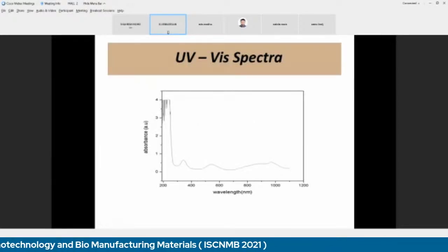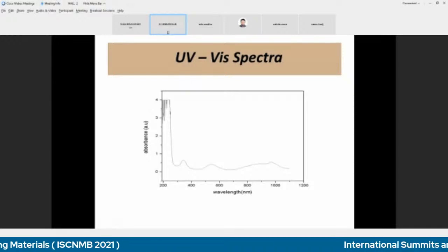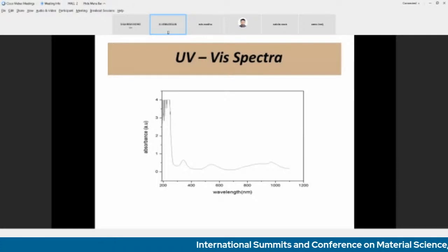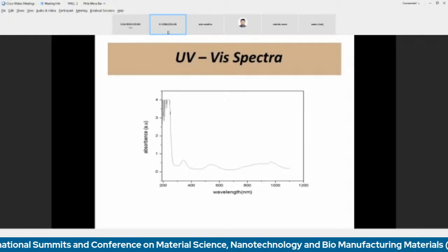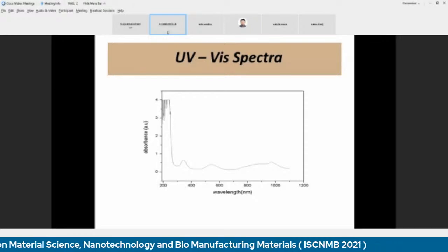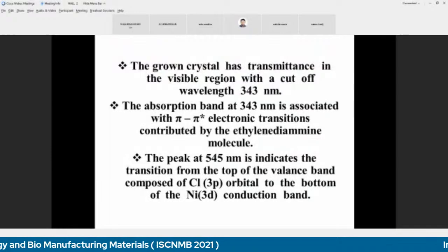Next, I am going to discuss UV visible spectroscopy. The UV visible absorption spectra was obtained on the ELICO SL 18 double beam UV visible spectrophotometer in the range of 190 to 600 nanometer at room temperature. From this UV visible spectra, we can find the grown crystal has good transmittance in the visible region with a cutoff wavelength